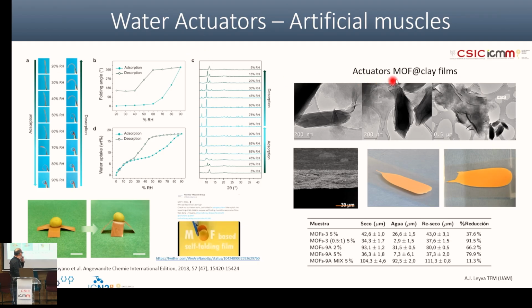Then here in Madrid, we are preparing that kind of films with our students, and with clays. We combine the MOF with clay, and here you can see the crystal of the MOF is micrometric, but it's totally integrated by the clay inside, so we are trying to solve the structure. The funny thing is we can prepare films, continuous and homogeneous, millimetric, with micron-sized crystals that are not easy, thanks to the clay. But we can do the opposite. Here you can only see the clay, well here also, but in the SEM you will only see the crystal. And we integrate really nanoparticles of MOF almost everywhere.